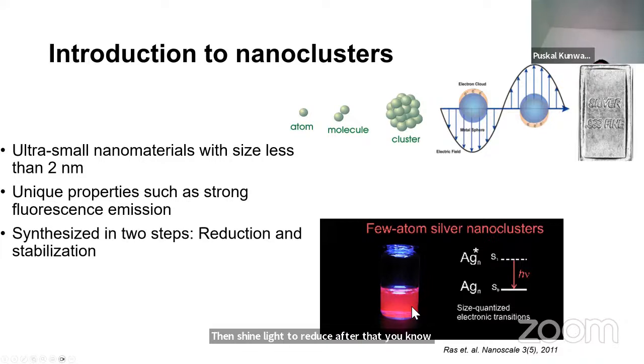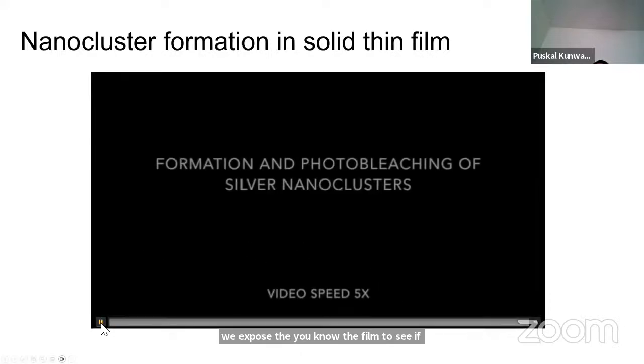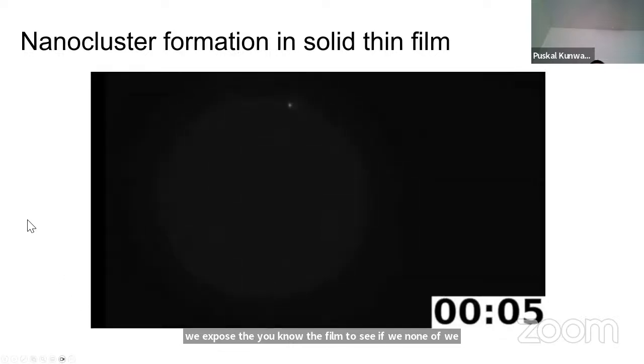Now what we did was we took PMAA, polymethacrylic acid, and silver nitrate, and spin coated thin films on a microscope cover slip. Then we exposed the film to see if we can form nanoclusters or not. So it's a video. At around 1 minute or so, you will start to see the formation of nanoclusters marked by strong fluorescence.